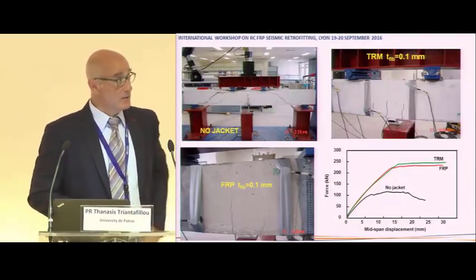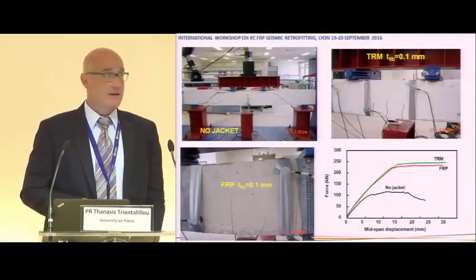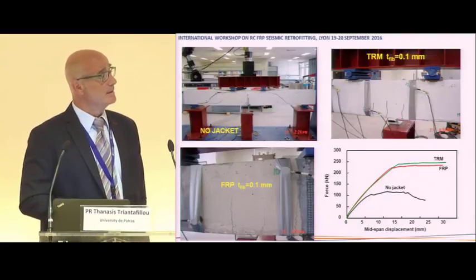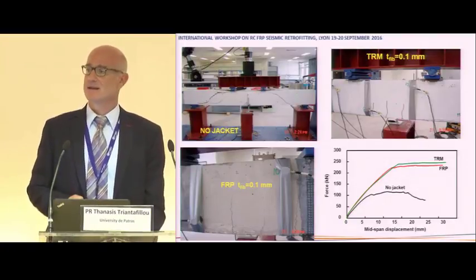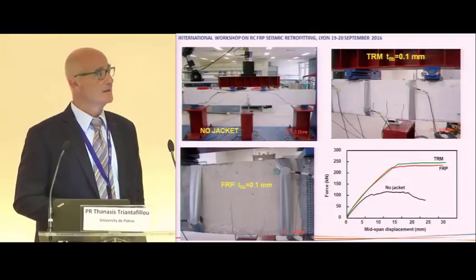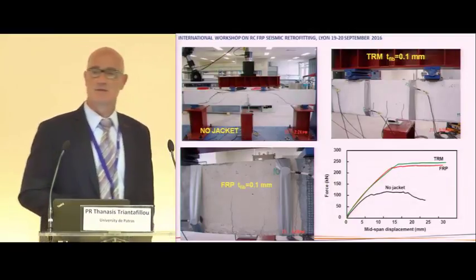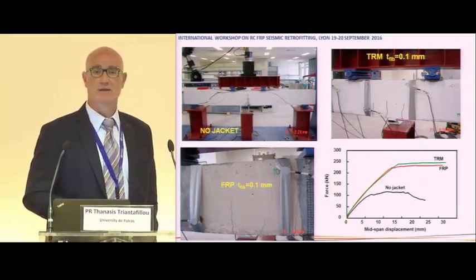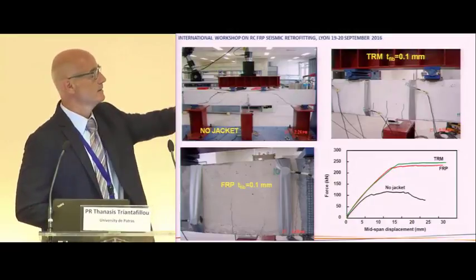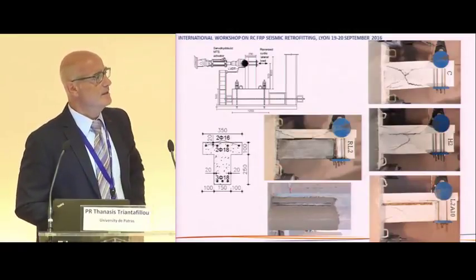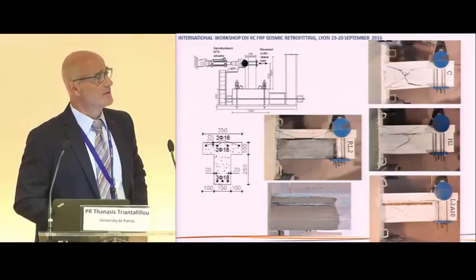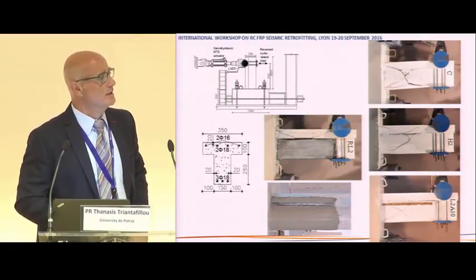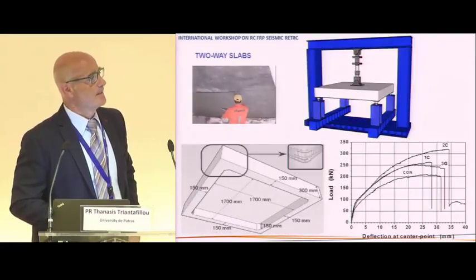The system can also be used to do shear strengthening of beams, for example. The effectiveness here is not as high as in the case of FRPs due to slippage of the fibers if we're talking about glass or carbon rovings. It is also effective when it comes to shear strengthening of T-beams, not only rectangular cross-sections, but also T-beams.